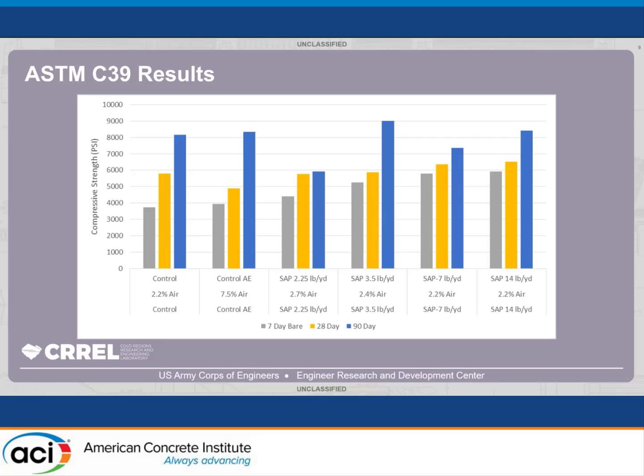The one mixture that we saw pretty comparable to the control, and not a lot of huge strength gain after 28 days, was our lowest dosed SAP mix of 2.25 pounds per yard. We'll go a little bit further into that as we see some more results.